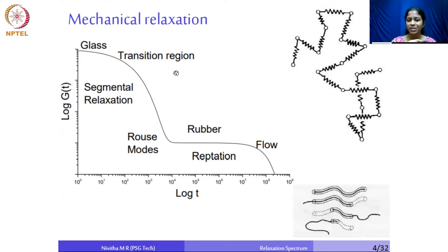We apply a constant strain and hold it there. We apply a constant strain over some time period. So during that time, the stresses will begin to relax. So we compute the stress, we divide it by the strain amplitude that we are applying, the constant strain amplitude, and what we get is the relaxation modulus. So this is how the relaxation modulus varies with time.